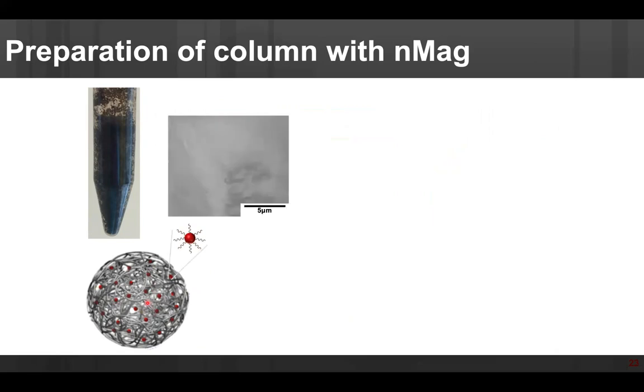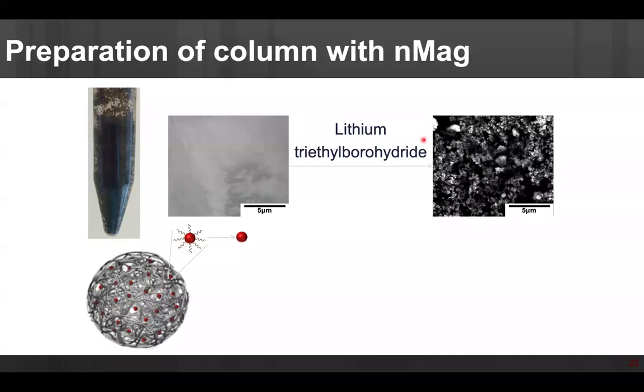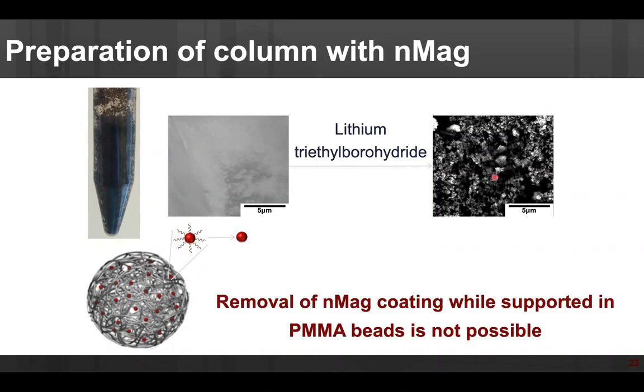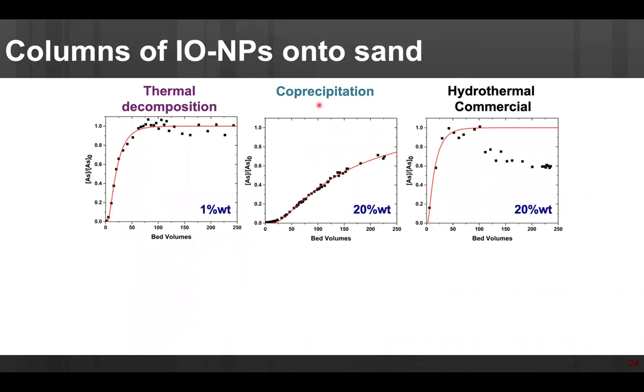And the idea was to try to image them. Those white spots are the nanoparticles, and it's bright because of the organic content. When I reduce that coating, we can see the particles depositing there, but this treatment destroyed the bead. So in the moment that you want to run something, it's basically a gel in there that doesn't let water flow. So because of that, we moved to sand, where I can do that kind of treatment without damaging the support.